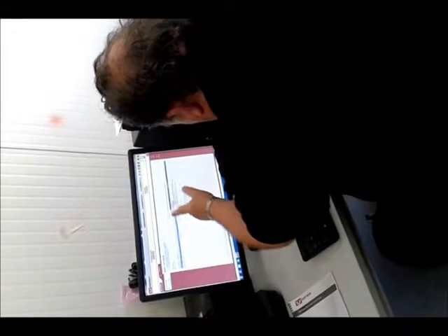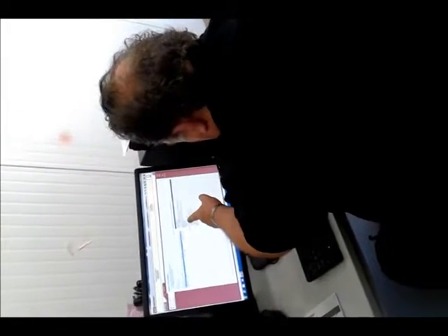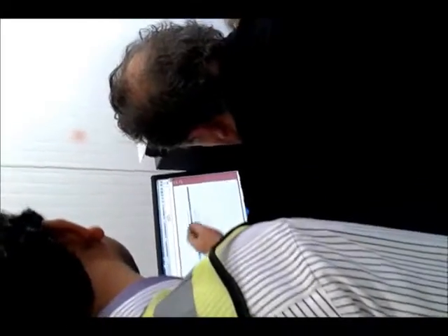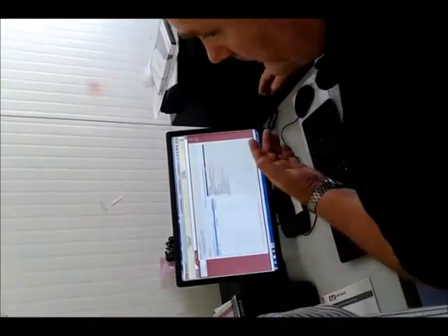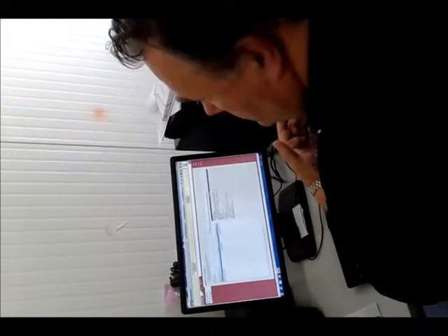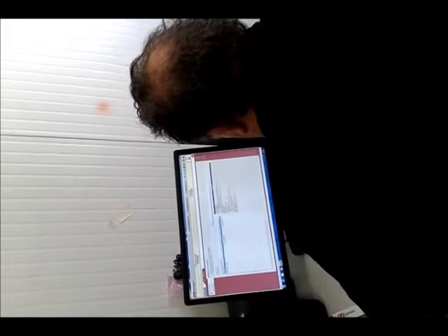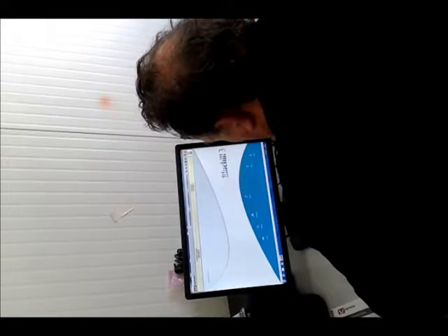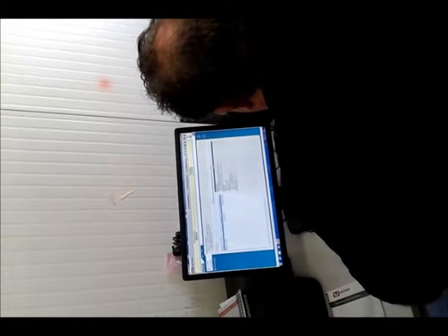Okay. So we're going to run a method. The description is that we're going to run at 0.05 millimeters per minute until we reach a set value. This is as per the standard, and then the speed will increase to 0.2 millimeters per minute. This is the rate of loading the beam. Okay. So if we go to test, that's what we're doing.